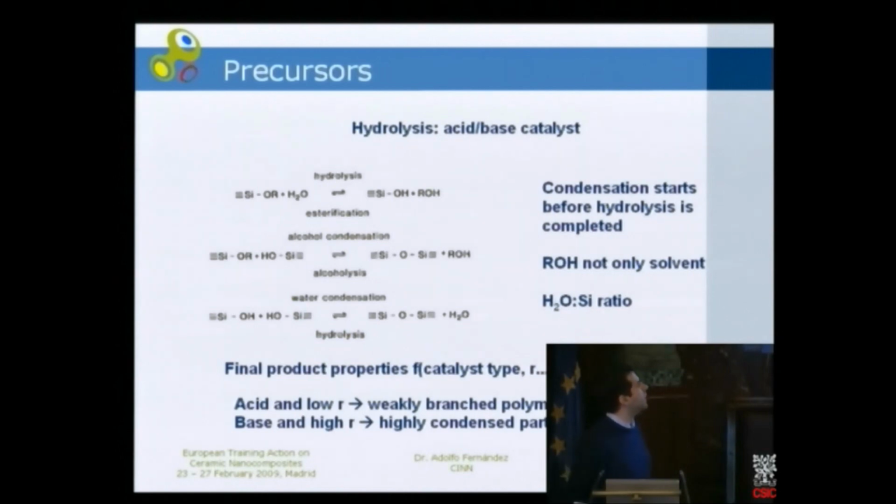As in the case of the transition metal complexes, the reaction mechanisms are the same with hydrolysis and condensation, but in this case, the condensation starts before the hydrolysis is completed. So the alcohol acts not only as a solvent, because it has influence in the final structure of the product. And it's also important to control the water-silicon ratio in order to control the final product properties.